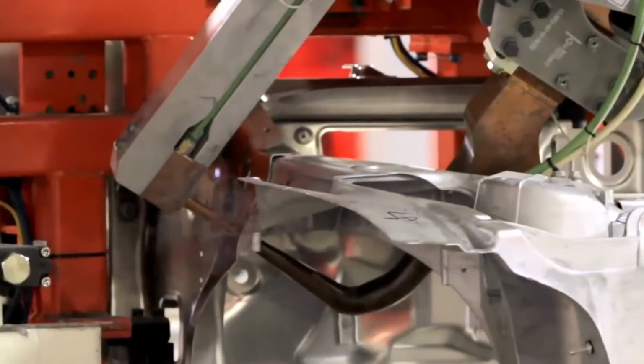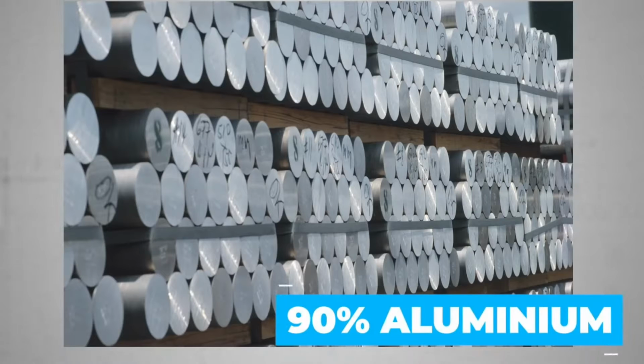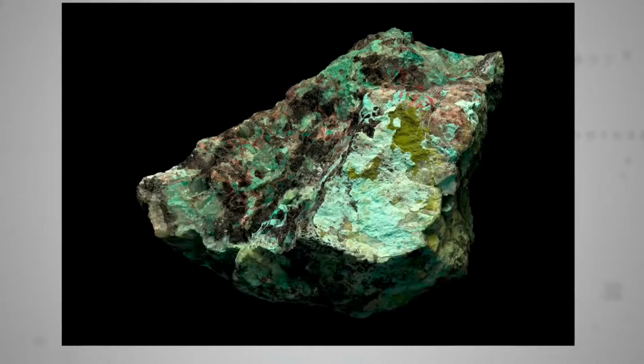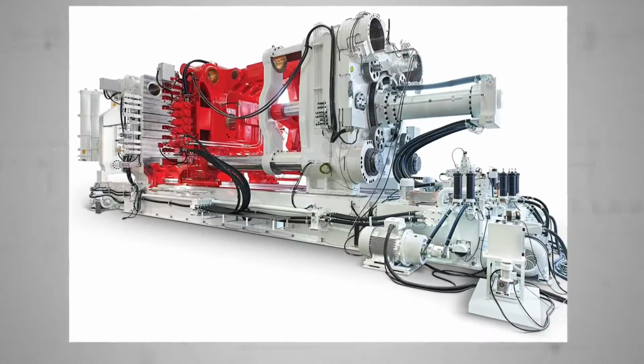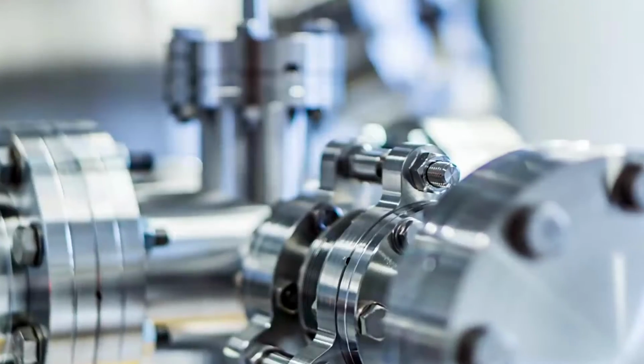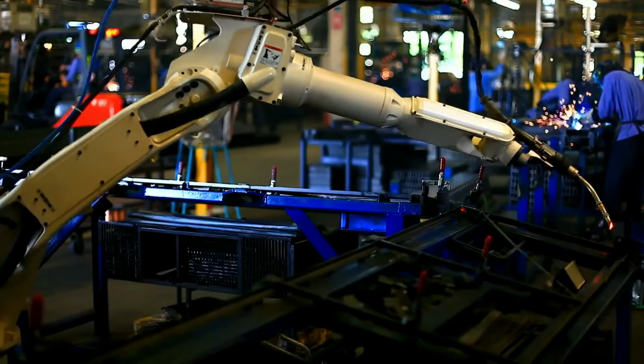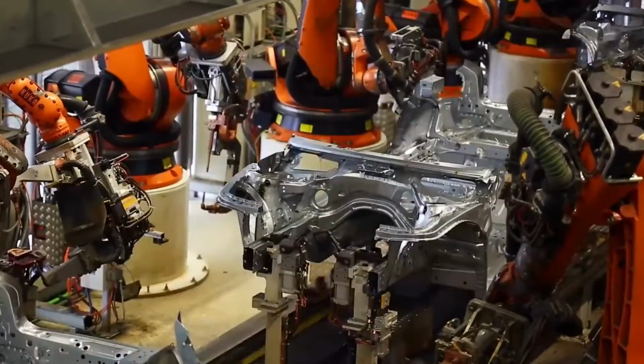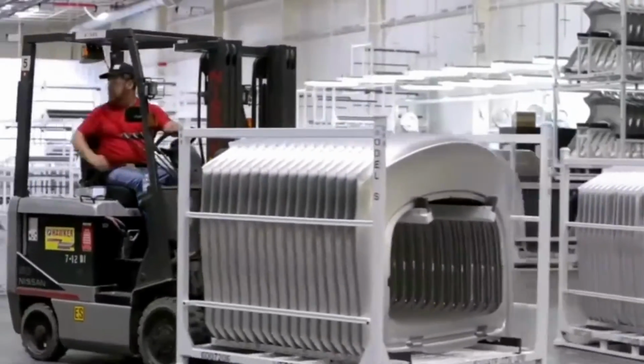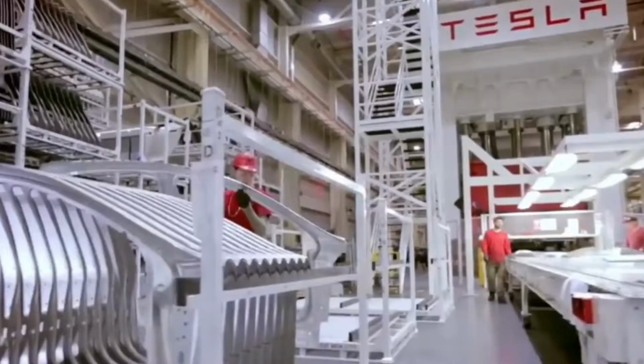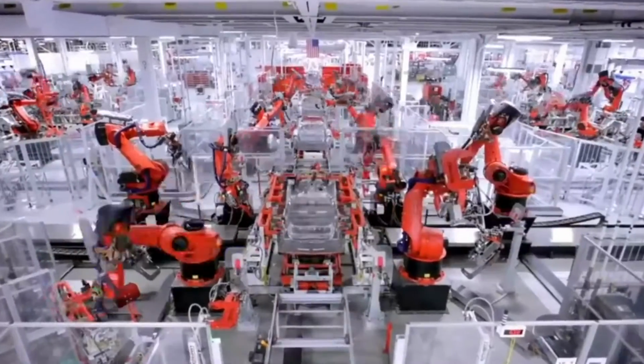To prevent the formation of oxides, a tank blanket of nitrogen gas covers the molten aluminum, which is circulated to maintain an even temperature. Argon gas and a rotary degasser are used to remove impurities, with a silicon carbide filter removing most other particles larger than 25 micrometers or 0.98 thou. At the beginning of each casting cycle, robots spray 35 milliliters, 1.2 imperial fluid ounces, 1.2 US fluid ounces, of soybean oil in a thin layer inside each half of the mold to allow separation.